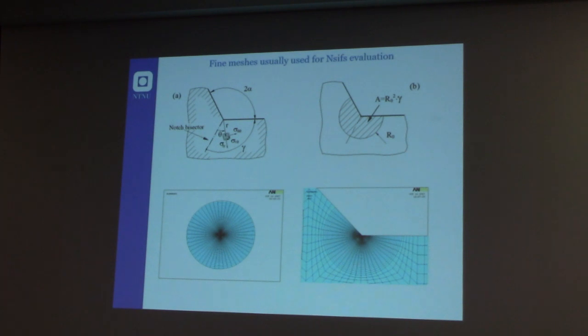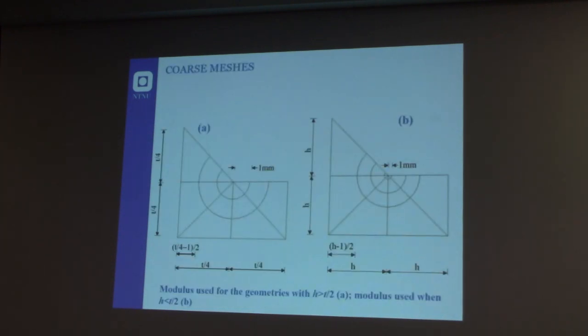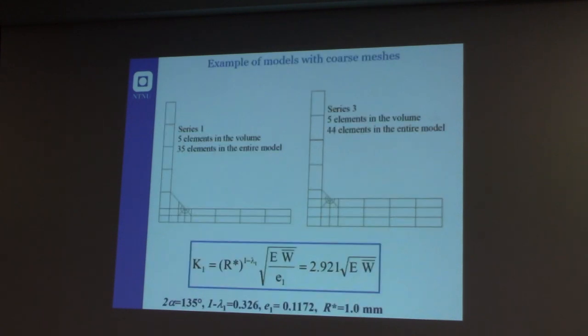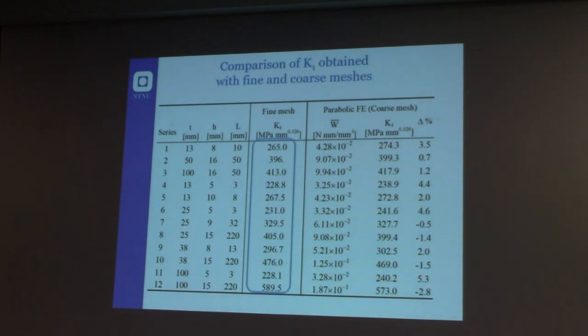if you consider three-dimensional models. So we gave some guidelines in a paper published in 2007 and also in a paper published in 2010 on how the mesh close to the crack tip has to be made to make the method efficient. After that we applied it to different configurations. What was found is that considering a fine mesh, you have this value of the notch stress intensity factor. And considering a coarse mesh, a posteriori you can derive the notch stress intensity factor from the strain energy density.